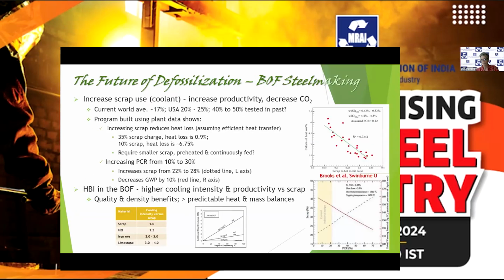Increased scrap use again in the BOF. There are two charts on the right-hand side from Swinburne University. They've been doing some work on increasing the amount of scrap used in the BOF. The current world average is 17%, and in the past, 45% has been used, but it wasn't sustainable because of scrap availability. Their program was built on actual data from the steel mills, and for a 35% scrap charge, they had a heat loss of less than 0.9%, but with a 10% scrap charge, the heat loss was 6.75%.